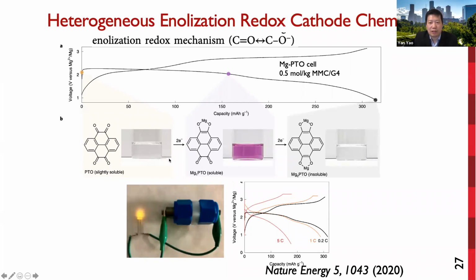So we probed the cathode reaction mechanism using UV-visible spectroscopy. The reduction of PTO in the magnesium electrolyte is actually a heterogeneous liquid-solid reaction. We use a Swagelok cell, discharge to different DOD, and then dilute the reaction electrolyte with DME. What we see is that the PTO is reduced to a soluble Mg1 PTO intermediate and then to insoluble Mg2 PTO. So the precipitation of Mg2 PTO is a spontaneous process that overcomes the solvent stripping from magnesium.